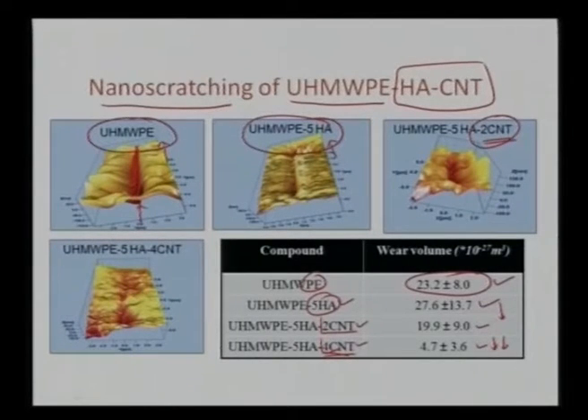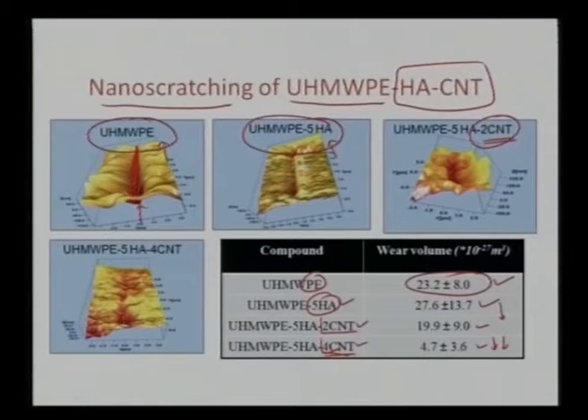It means I am achieving much more superior tribological properties once I have enhanced CNT reinforcement in the polyethylene and hydroxyapatite matrix. That is what we can see: once we have a poor interface between hydroxyapatite and polyethylene, I am seeing much enhancement in the wear volume, or my wear resistance is dropping off. But once I start reinforcing with carbon nanotube, I am seeing much more enhancement in the wear resistance. That is what is happening out here. So my wear volume is basically going down with the increased CNT content, and that is what is happening with the nano scratching in this particular case.